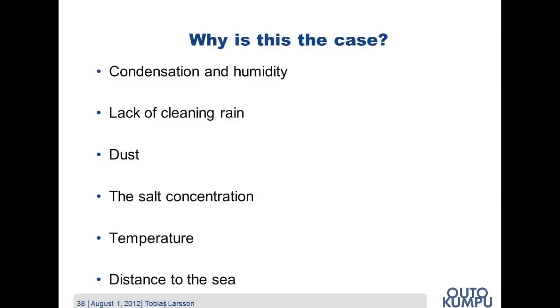Lack of cleaning rain is also a factor, since the material will never be naturally cleaned as in Europe. The dust will retain the moisture for a longer time and can create so-called deposits. The salt concentration, i.e. the chlorides, are the single biggest factor, since the chlorides are stainless steel's biggest corrosion enemy. And as you probably know, the salt concentration in the Gulf is considerably higher than most other oceans in the world. The high temperature also has a tendency to speed up the initiated corrosion process. And last but not least, the short distance to the sea makes it a very aggressive environment.